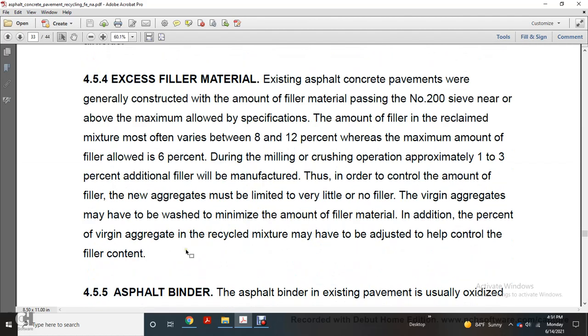Excess filler material: the existing asphalt concrete pavement is generally constructed with the amount of filler material passing the number 200 sieve near or above the maximum allowed by specification. The amount of filler in reclaimed mixture most often varies between 8 to 12%, where the maximum amount of filler allowed is 6%. During the milling and crushing operation, approximately 1 to 3% additional filler will be manufactured.